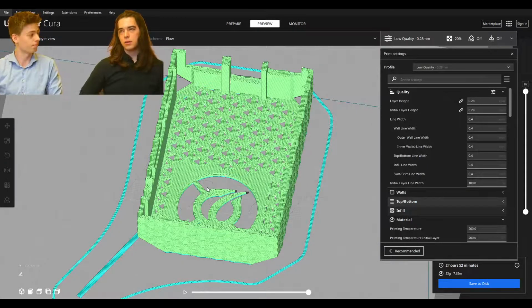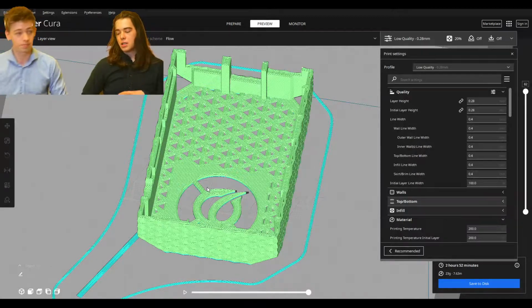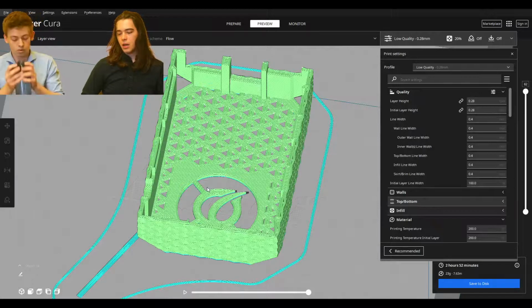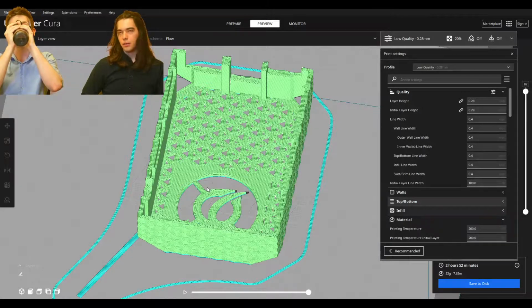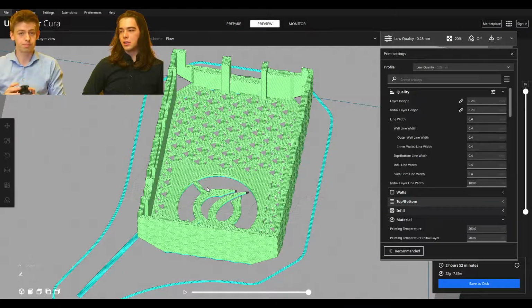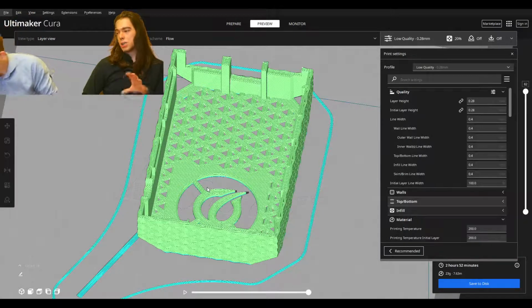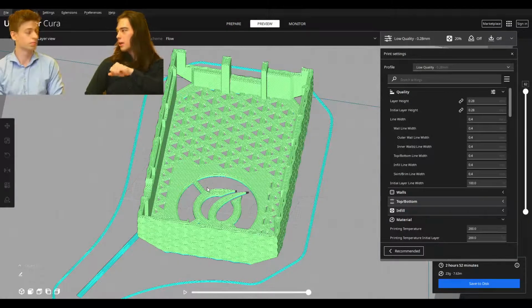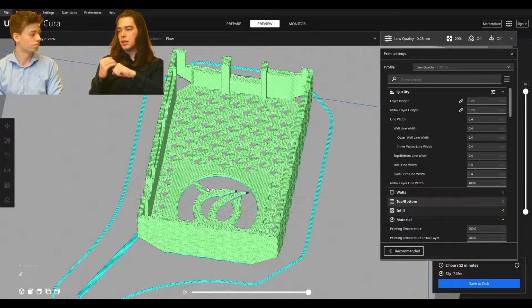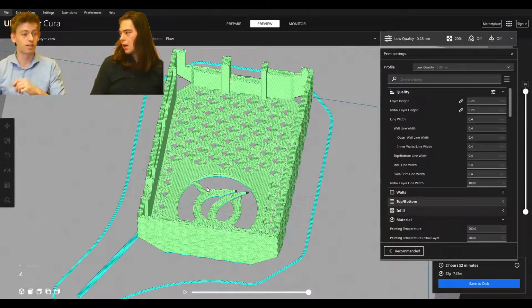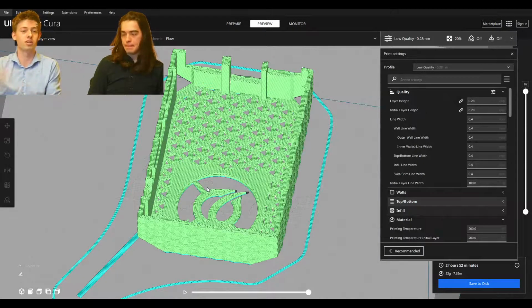I know there was a paper written, not about first layers but about interlayer adhesion, saying that a higher thermal mass or thicker layers were generally stronger, because more material is coming out at once and it's cooling down slower. Whenever you do the line right next to it, it's still warm enough that you'll get cross-linking or whatever. Well, 3D printing is basically welding. Yeah. If your layer doesn't partially remelt the layer below it, then it won't actually stick to it. It'll cause all sorts of adhesion problems.